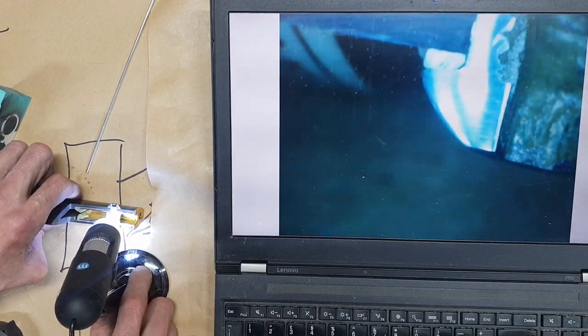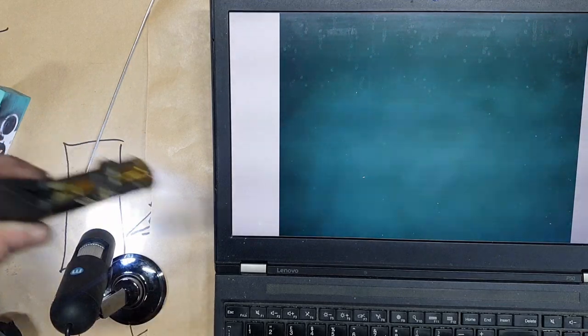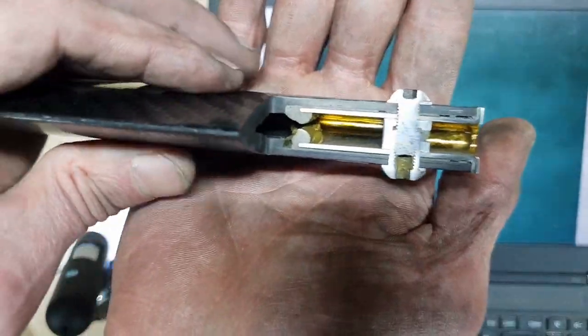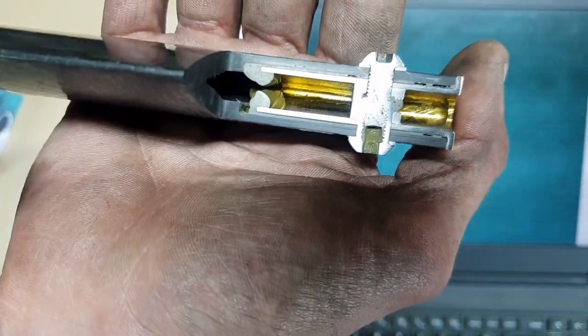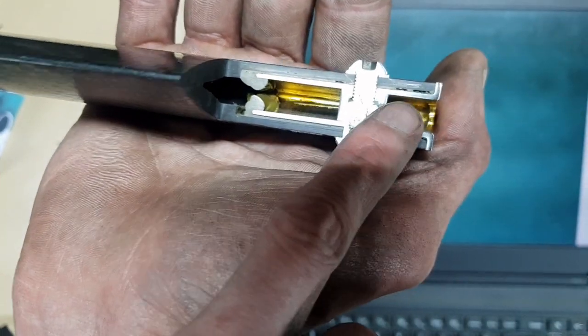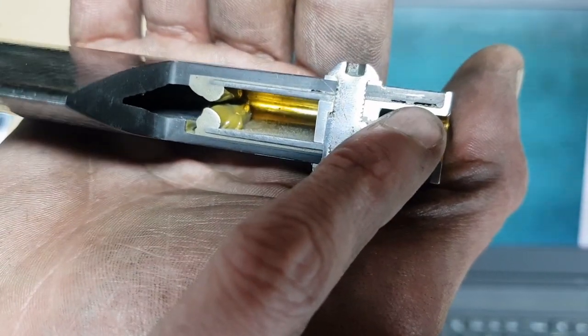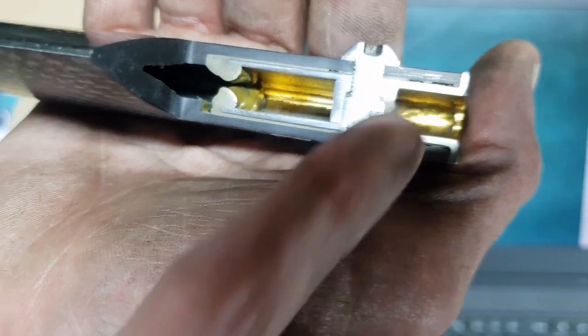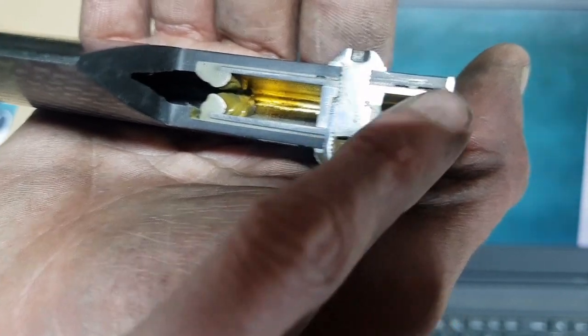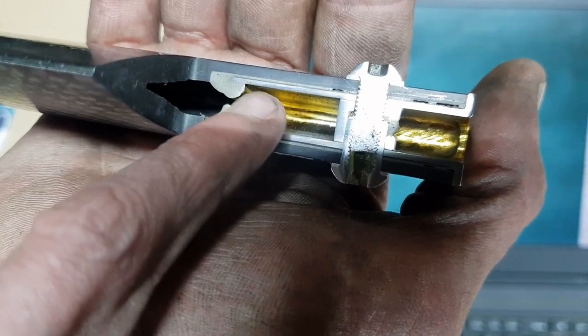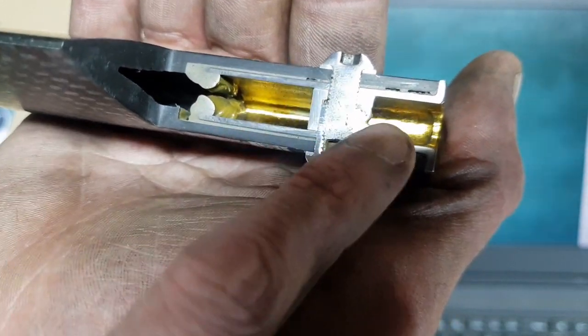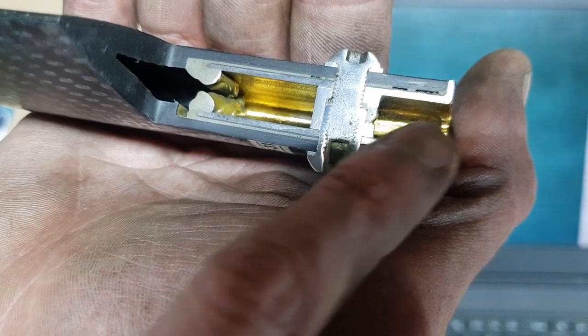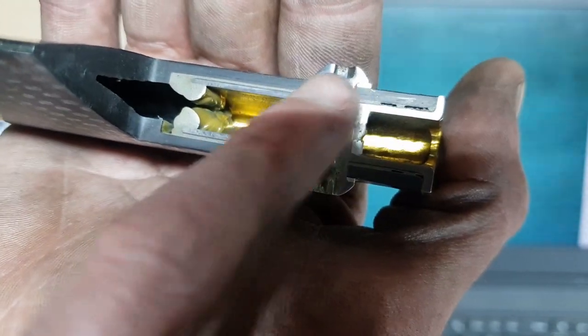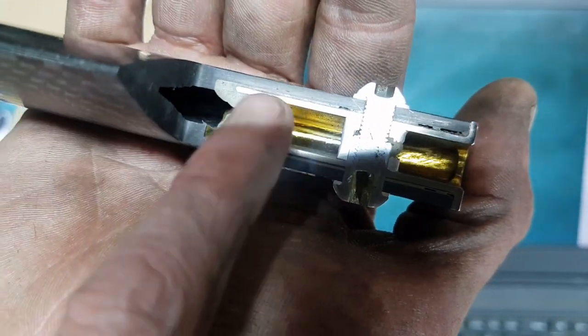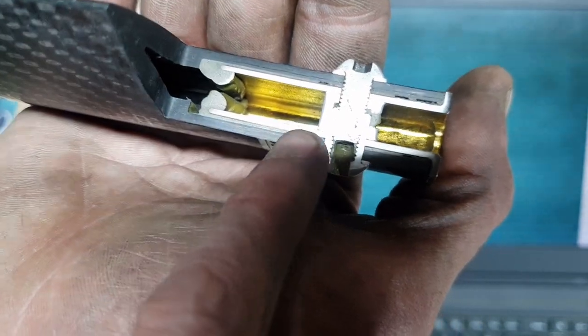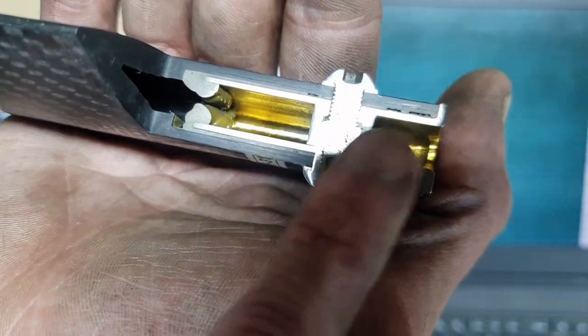So that's kind of that. Bring it up to the camera again. You can see the part there. They're the voids, which are not good. That's, I would imagine, because there's no taper on this part here, it would be very hard to get that clean of a line. So I would imagine that the insert was coated with epoxy. The wishbone was coated with epoxy. Once it's machined, you can see where it's machined there to accept the insert.